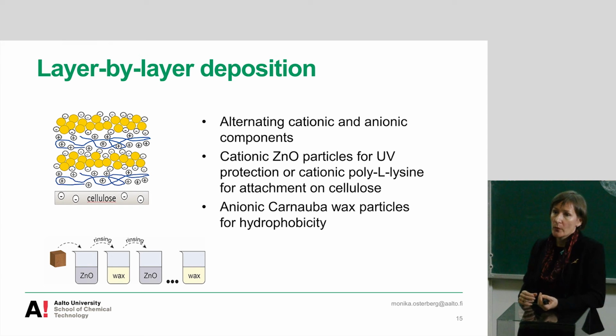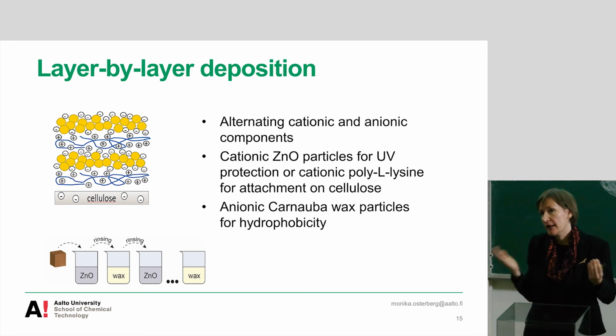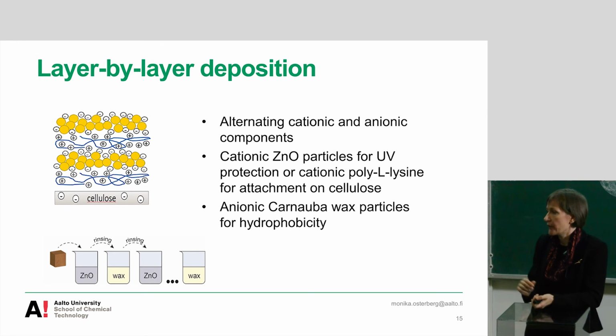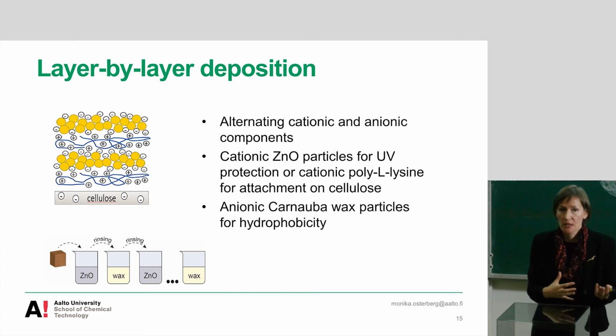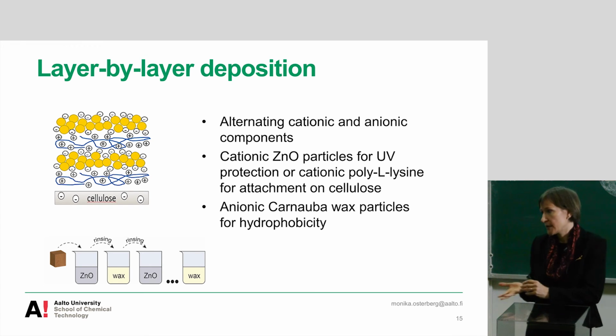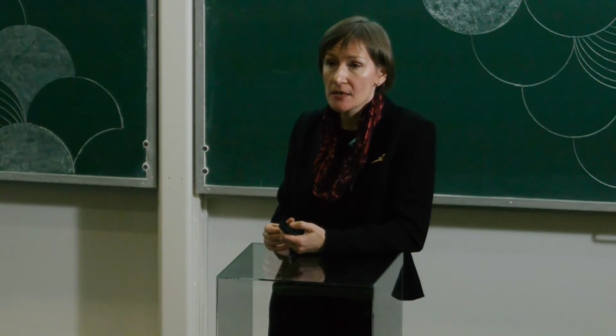That's a very simple way of surface modification. You just alternate the cationic and anionic components on the surface. And in the case of wood, as a cationic component, we used zinc oxide because it gives the UV protection. We did the same principle for the textile modification, and here we used polylysine as a cationic to get it to stick better to cellulose. And we continued with the wax particles because they were working well.